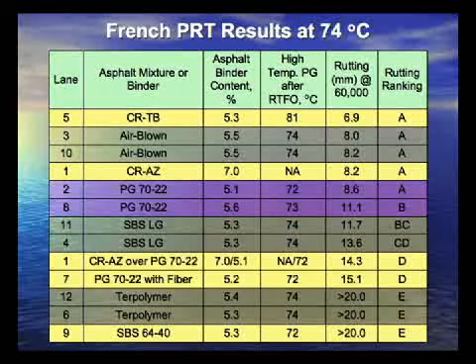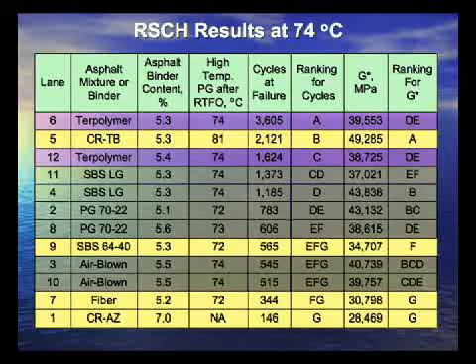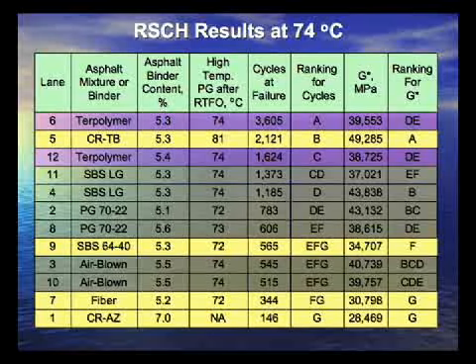What we see is a clear ranking here, and the French rut tester, which is basically a large pneumatic wheel in a confined box. We see a similar type of ranking, a clustered ranking that we kind of saw under the ALF. And this will also be correlated to the rutting under the ALF as well. Repeated shear at constant height, that's the SuperPave shear tester. Before we started getting involved with the simple performance tester, this kind of gave some good ranking. We can either look at repeated shear or the modulus.